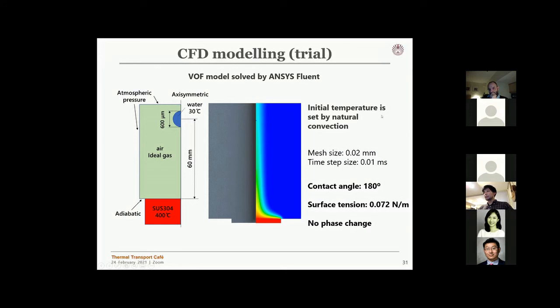The initial temperature profile is set by natural convection. We calculate this temperature profile before we induce droplet impingement. And also, we set the contact angle as 180 degrees so that we can sort of simulate the film boiling regime.